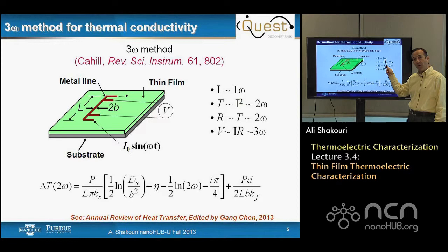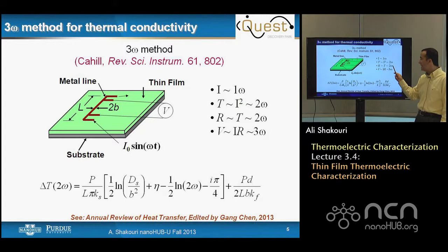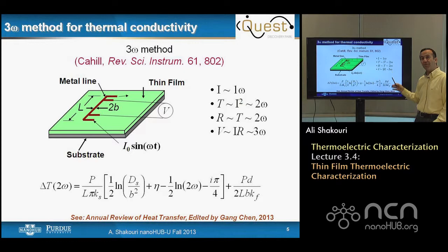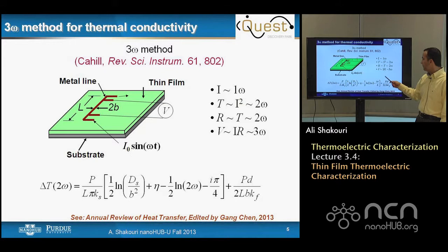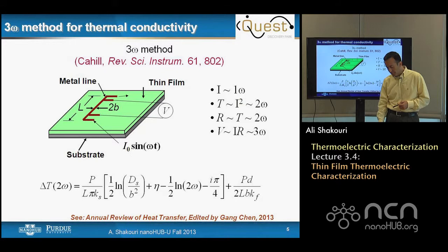Cahill's idea is that if the current is modulated at frequency omega sinusoidally, the temperature increases due to Joule heating with a component at two omega. Resistance in the linear regime is directly proportional to temperature, so it also has the same two-omega component. If you measure the voltage across the line, voltage equals current times resistance, giving a three-omega component — that's a good way to extract the temperature-dependent property. Analytical expressions relate the extracted temperature increase to thin film conductivity, though these are approximations valid when the film thickness and line dimensions are in the right regime.